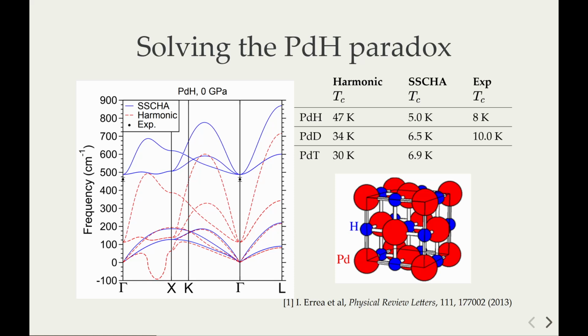We can also see the difference in the prediction of the superconductive critical temperature using the harmonic approximation, which indeed shows us the standard isotopic effect. While using the self-consistent harmonic approximation, we see this inverse isotope effect, which is much closer in agreement with experiment. The agreement is not perfect, and this is a work in progress - this material is very interesting and seems to have nonlinear properties also in the electron-phonon calculation, which are required to improve agreement even further, but this is not the topic of this talk.